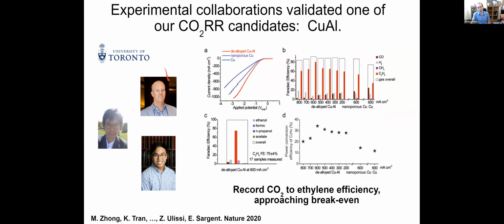Our collaborator, Ted Sargent at the University of Toronto, spent a lot of time digging through and trying to verify these. Anyone who's done electrochemical experiments knows that it's not just enough to know the right composition. There's a ton of engineering that has to go into making it high surface area, tuning the structure, really making sure you understand the synthesis conditions and so on. Once we identified this copper aluminum material, his students took the extra time to really optimize this material and really dig into what the limitations were.